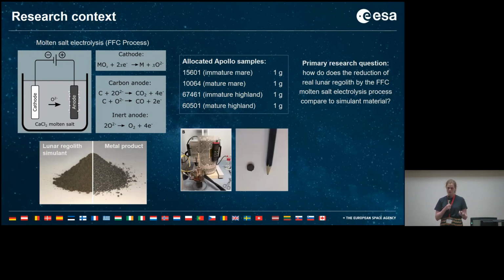The samples are large for Apollo samples, but small compared to what we normally process, and we wanted to do a repeat with each sample, so we're processing 500 milligrams at a time. So we've built a miniaturized small electrolysis cell, and then we have to figure out a way to retain the material in the salt. So we've decided to sinter it into a pellet prior to processing, so we don't lose it as a powder in the salt.